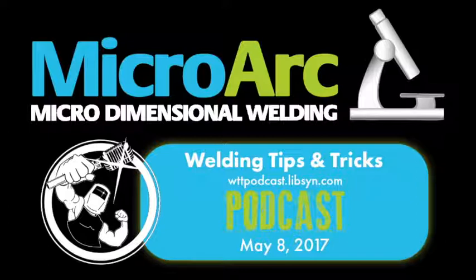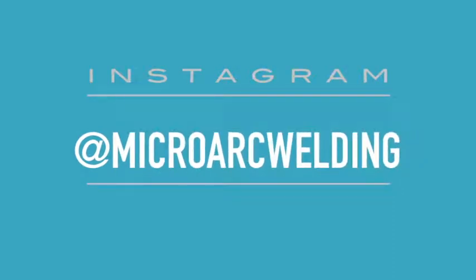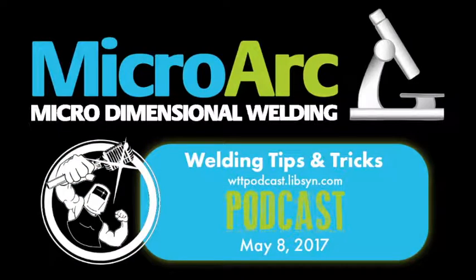One thing I noticed when I got a little taste of laser welding, and they're awesome, they do an awesome job and they definitely have their place. But we were qualifying some parameters, so we would run some beads, and then section them, cut, polish, and etch, looking for spot overlap and things like that. Even at that low intensity, low heat input, on a small coupon, 20 or 30 thousandths thick Inconel 718, with one bead you would see some deflection because of the gradient of heat.